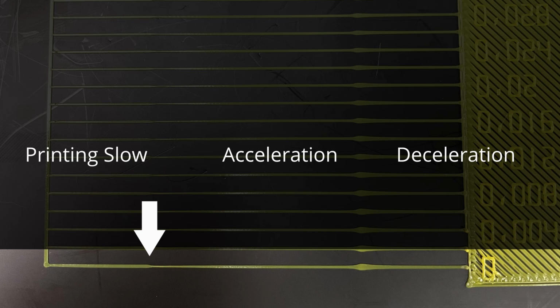I'm going to focus my attention on the bottom line. This is with zero pressure advance, none. It should be a consistent line width all of the way across. But obviously, it's not. We can clearly see under extrusion where our print speed transitions from slow to fast here on the left side. Look how the line tapers from thin, then back to a normal printing width. There is some over extruding when the printer changes speeds from fast to slow here on the right side. This is why you see bulging corners when printing cubes. Just past the blob, you can see the printed line tapers again from wide back to its normal printing width.